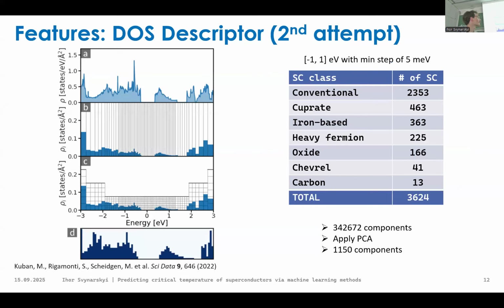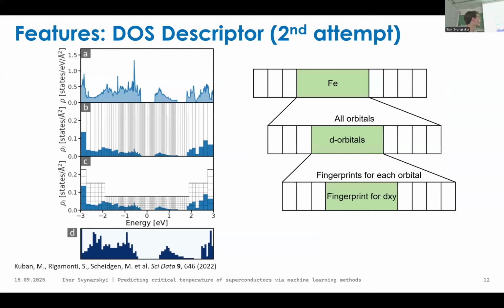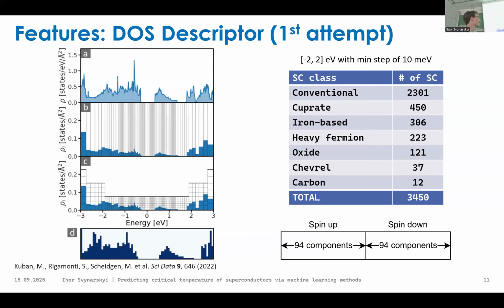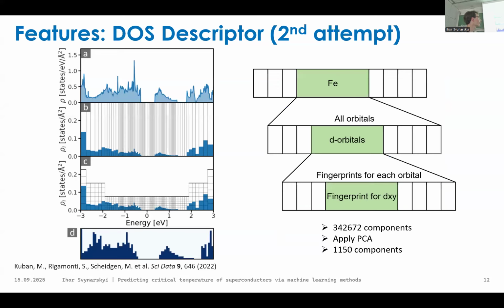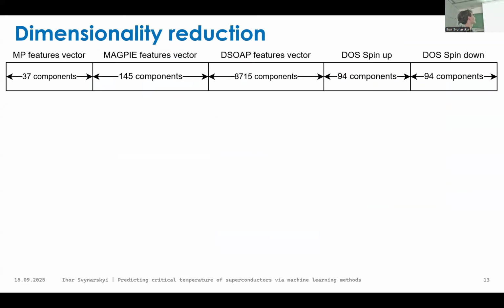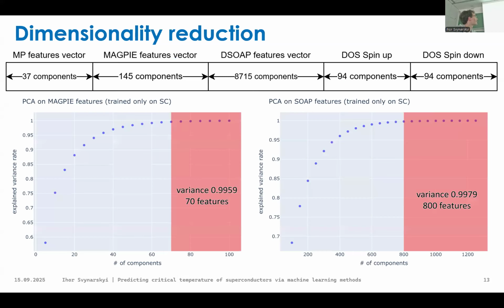And yes, in this case, the number of compounds was this one. So we tried to do it for a smaller region around the Fermi level with a slightly smaller step. And because of this smaller step, the size of this fingerprint for a single orbital was almost 500 components. Yes, so in total DOS, we used a bigger step, but also a bigger region, but it resulted in only like 200 components. And so basically, our total data set would consist of some Materials Project features, chemical features, this averaged local descriptor, and spin and density of states descriptor. And then we are trying to apply dimensionality reduction on these blocks, not on the whole vector, but only on these blocks, because they are of the same nature, and we can try to do it first on them.